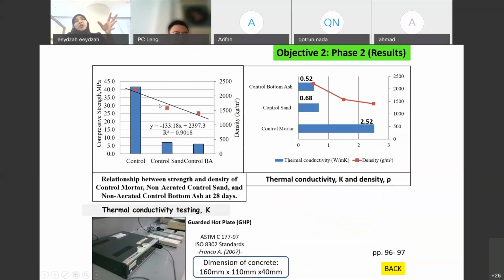So of course the control strength is very high because it is not aerated. It has no pores. But I compared with control sand and control bottom ash, and it has quite similar performance. As long as it's achievable, for a normal non-load bearing wall, we need to at least achieve 5 megapascal. So at least I'm achieving the standard requirement of UBBL.